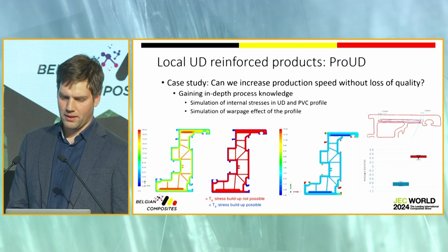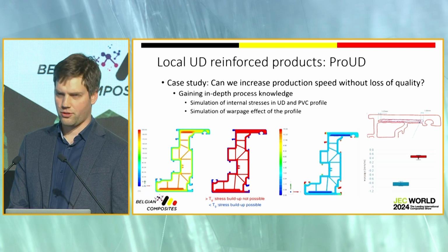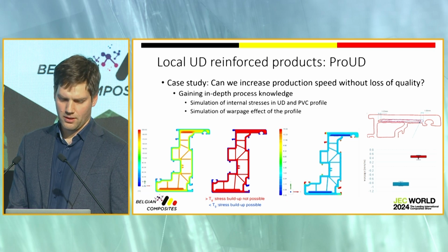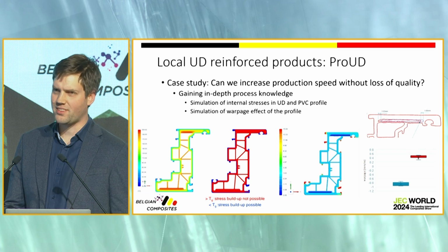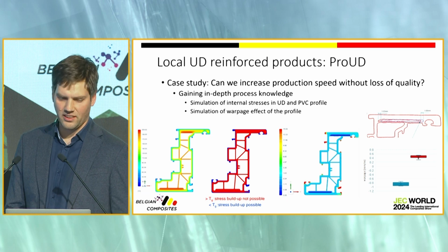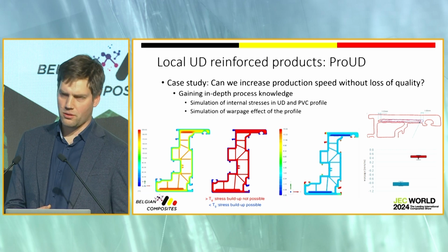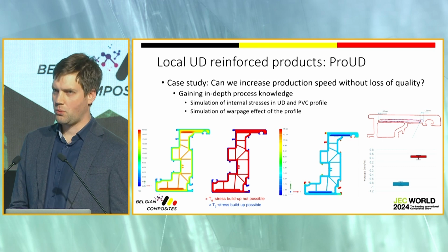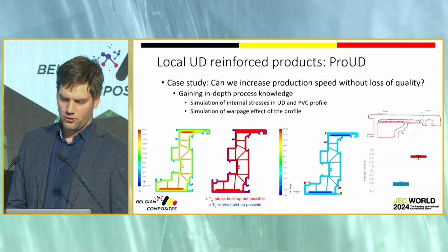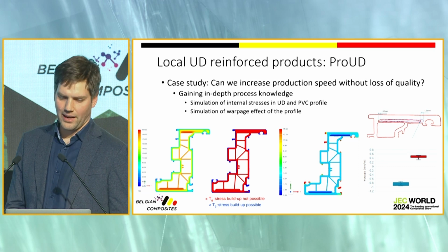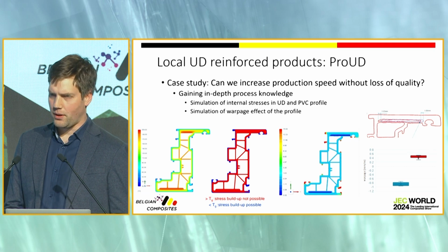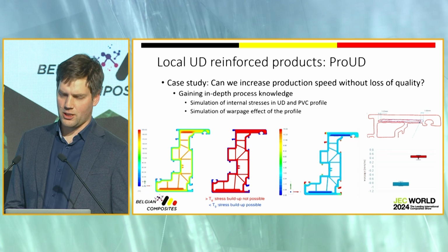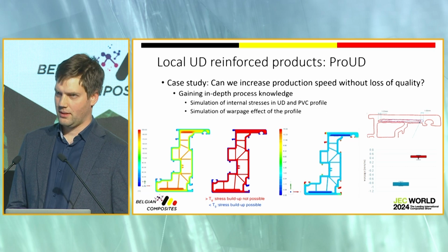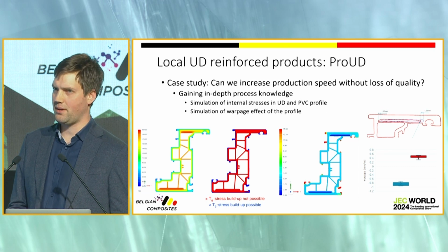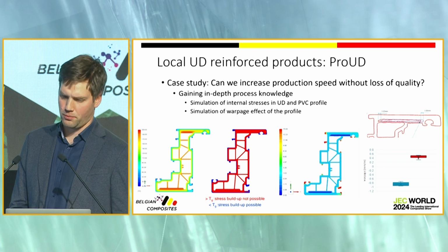We also implemented a lot of numerical simulation in predicting, first off, of course, the cooling behavior of these profiles, but linked to the cooling, you have the stress buildup because you have different CTEs, glass fiber versus the matrix versus the PVC, which tends to warp the profile. So we, of course, need to tackle this. And it's very important that we know the effect of the glass fiber tape inside the profile. A little bit of repositioning of the tape can lead to a completely different warpage of the profile.